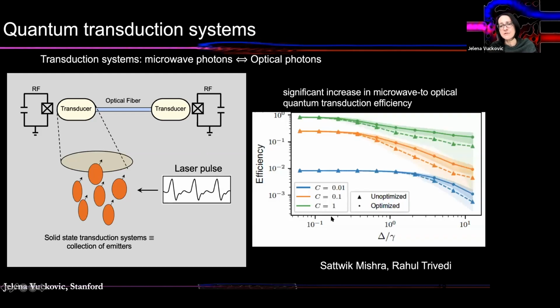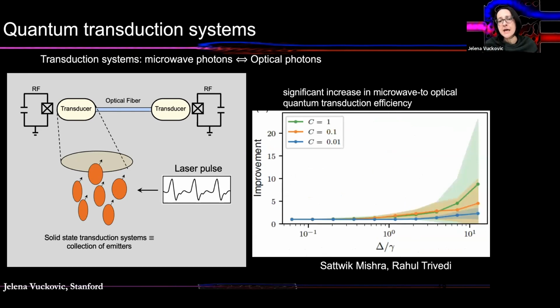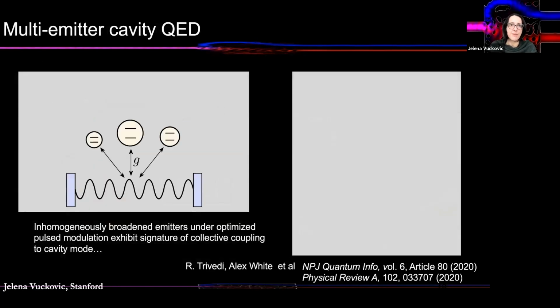And our theoretical results indicate that this is possible. In fact, this degradation in transduction efficiency that occurs as a result of large inhomogeneous broadening can be recovered by optimizing driving on the system. This could be laser driving or microwave driving on all of them, and it's the same set of electrodes on all 10 emitters together. So basically, we see improvement in transduction efficiency of about 10 to 20 for random system of quantum emitters, which is quite exciting. And we're actually looking into doing this experimentally.